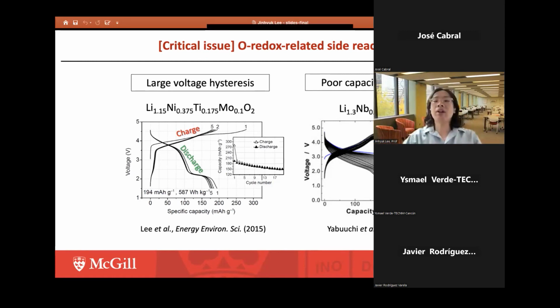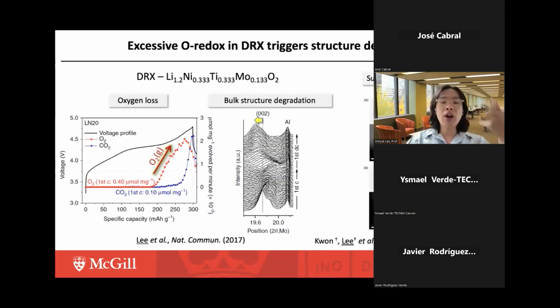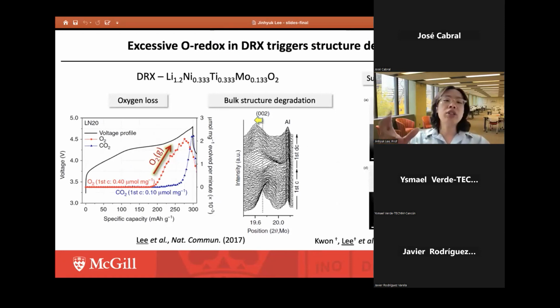So we see that there's a lot of cycling stability and cycling performance issues even after we designed this disordered rocksalt material with some interesting strategy. And we found that this is largely due to the excessive oxygen redox process that happens in the DRX material, which triggers a bunch of structural degradation. So for example, on the left side, I'm showing you the oxygen loss profiles, the gas evolution. And the middle part, I'm showing the in situ XRD pattern of the DRX lithium nickel titanium molybdenum oxide.